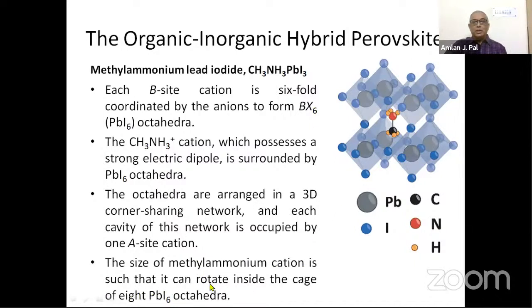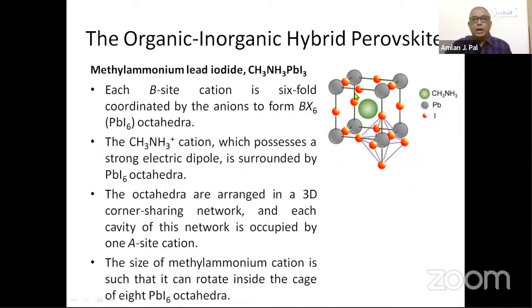Not only that, it can rotate inside the cage of the PbI6 octahedra. So everything is important. I will show you later that the size of the cage is so optimum that it allows the methyl ammonium cation to rotate inside the cage. So everything is important in this particular material. Here is a mirror picture. I have lead, iodine, and then in the middle I have the methyl ammonium, at the cage.